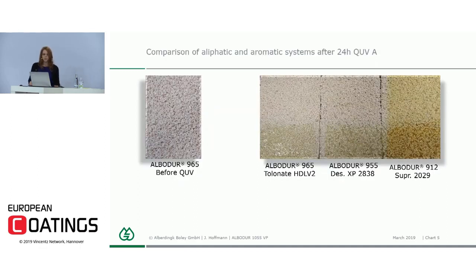Here we can see how formulations normally look, which are used for stone carpets. We used here a marble kind of flake and then tested the samples in the QUV. You can see here we have the standard before exposure and then the other samples afterwards. And even after 24 hours of QUV, we already see a color change. That color change is caused because castor oils normally are not very heat stable, and the heat which is developed in a QUV machine is relatively high. That is one of the big issues we're always facing when we develop a product like this, that the reality is quite different than the QUV machines are.